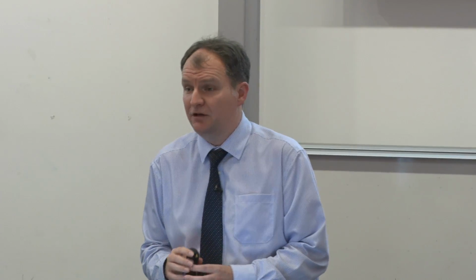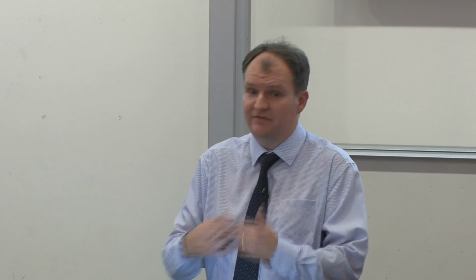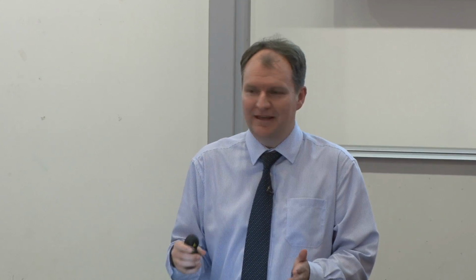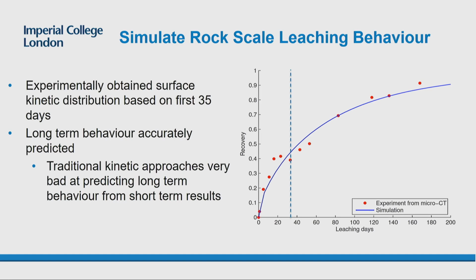And we can really accurately predict the long-term behavior, which is important because people do a lot of these sorts of leach tests, and it's usually very hard to predict the long-term behavior from the short-term trends, or at least from the macroscopic short-term trends. And so we can do these sorts of experiments in 30 days compared to 6 months or a year you might do for the full leach test.